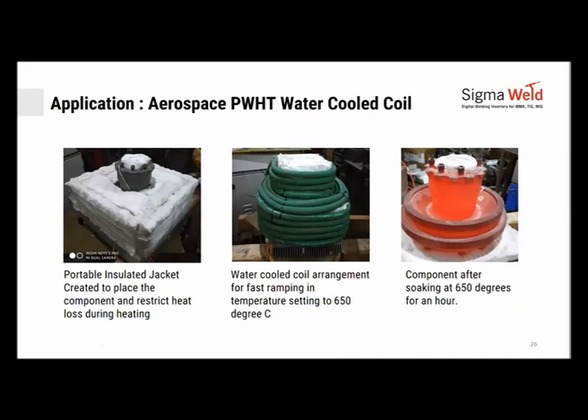Another very critical application for aerospace right now. This material here is non-magnetic and also has a very typical challenge where it needs to jump from 650 to 850 under 2 minutes. Otherwise, the heat treatment won't be correct or it will not reach its desired solution.